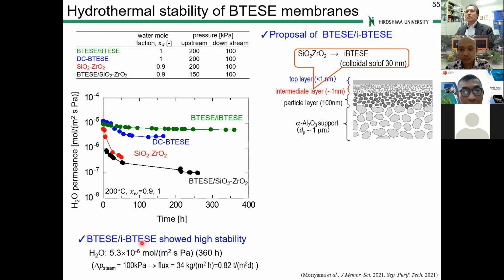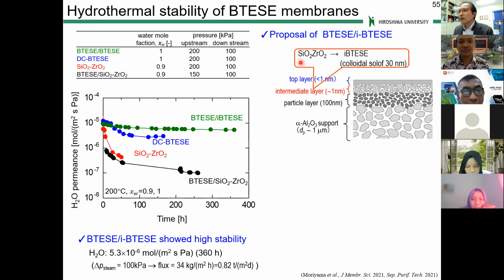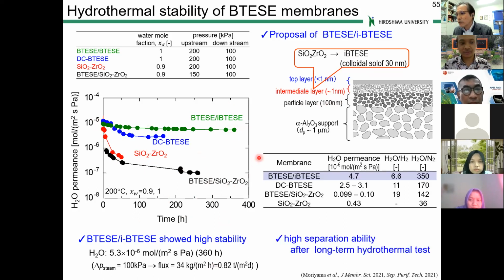Okay. Now we also propose increased hydrothermal stability of BTESE derived membranes. As I explained, the intermediate layer was prepared from silica zirconia, but we proposed the use of colloidal BTESE as the intermediate layer. Here we have some results of the stability as a function of time, more than 300 hours. Conventional BTESE membranes coated on silica zirconia show decreased water permeance, but BTESE coated on the BTESE intermediate layer, which is hydrophobic, is very stable as long as 360 hours, with, of course, high selectivity of water vapor over nitrogen.